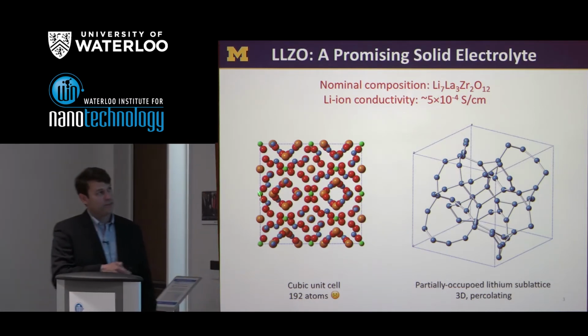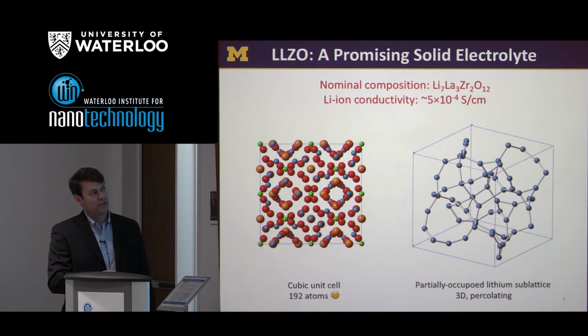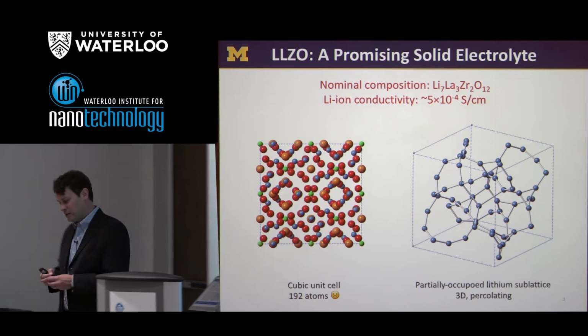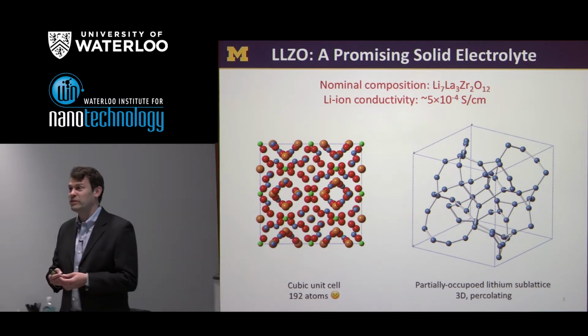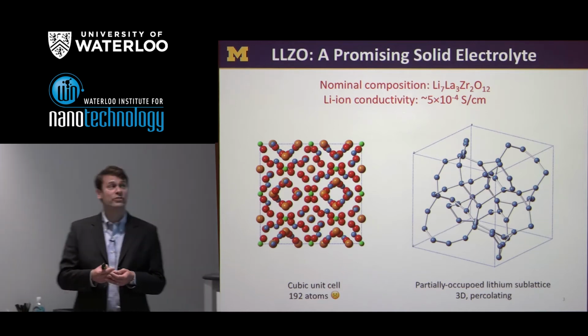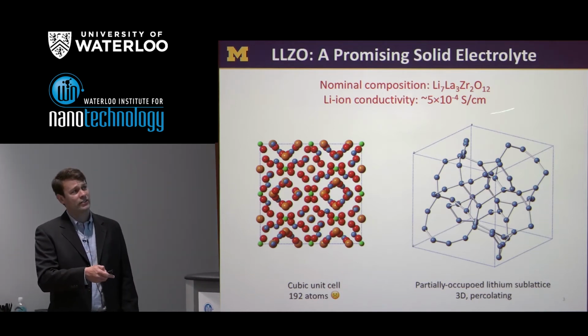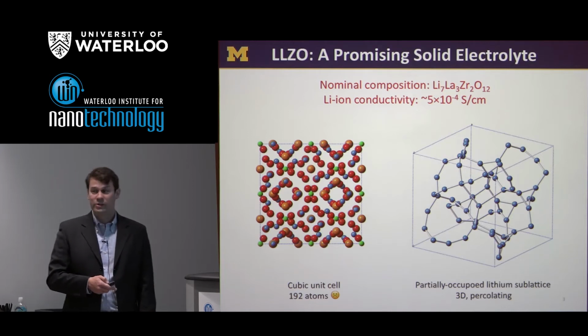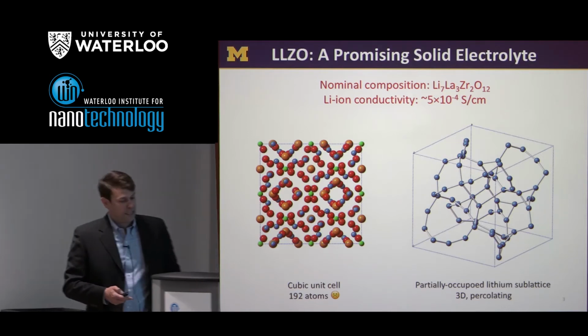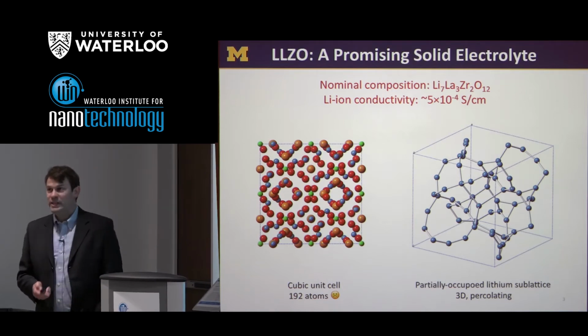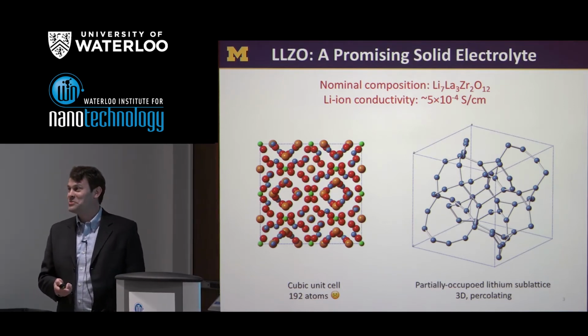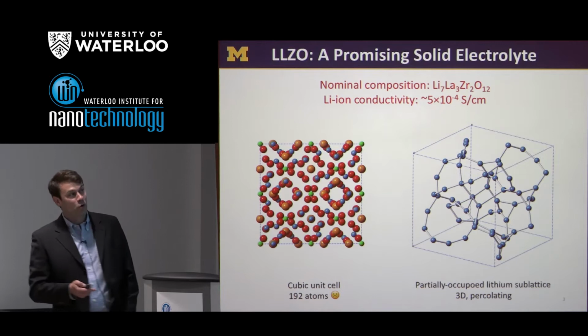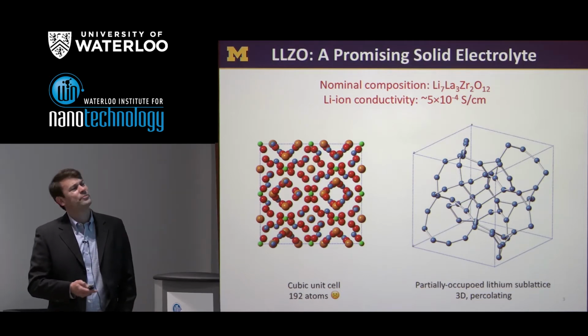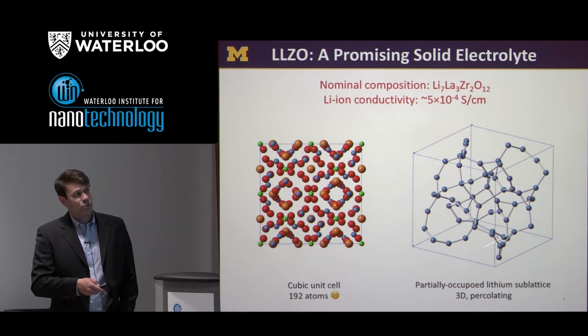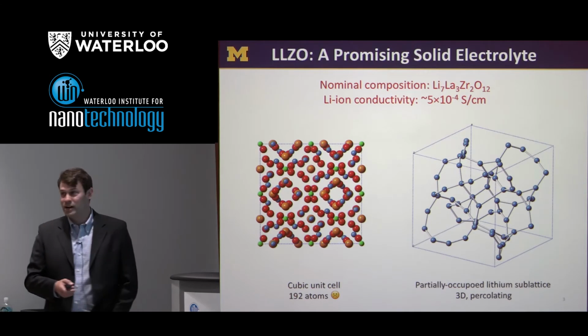I'm showing on the left the cubic unit cell. LLZO can in fact adopt two different polymorphs. There's a tetragonal and a cubic phase. It's the cubic phase which we're most interested in, because this is the one that gives us the highest ionic conductivity. And as you can see, it's a complicated system, about 192 atoms in that unit cell. For someone who does quantum mechanical calculations, 192 atoms is a challenge, just based on the quantity of electrons there.